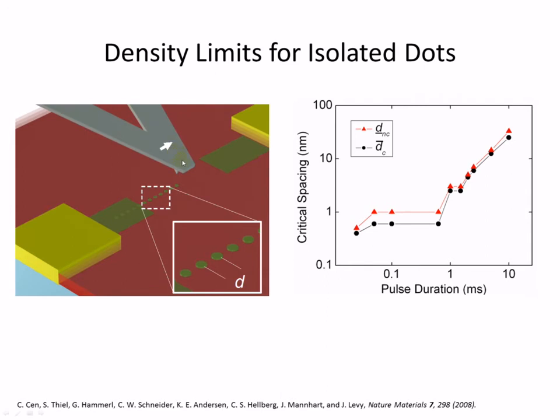We did an experiment where we looked at the insulator to metal transition, where instead of applying a continuous voltage, we used a voltage pulse that was on for some duration that ranged from microseconds to milliseconds. We pulsed these islands and separated them by a distance d, and looked for a sharp transition where below some critical distance these dots were overlapping and led to conduction between these 2 leads, and above which it was insulating. What we found is that at about 1 nanometer we were able to create structures that are distinct on the scale approaching 1 nanometer.